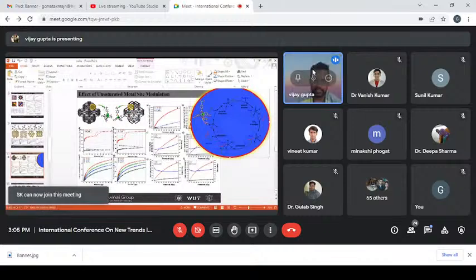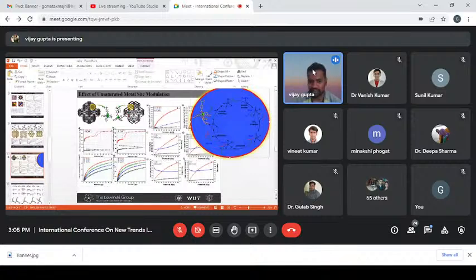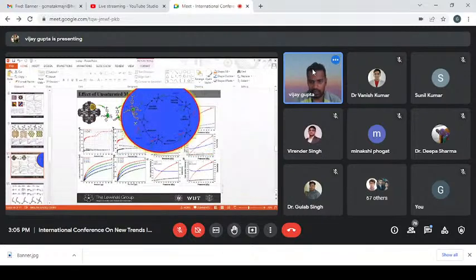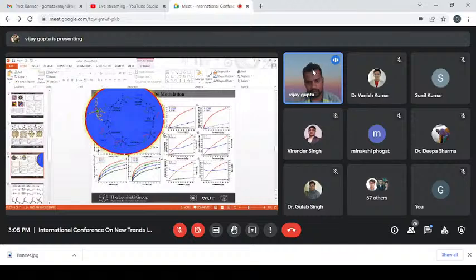So here we can see we have used different metals, same ligand, same carboxylate, same neutral ligand, and we have isoreticular structures. In isoreticular structures, we have similar structures, and if we see this CO2 profile, the CO2 adsorption is also very similar. There is not much difference. But when we talk about the selectivity, where we have unsaturated metal site, selectivity numbers are much higher. Here it is 80 and 125, and for methane it is 7.5 and 50.